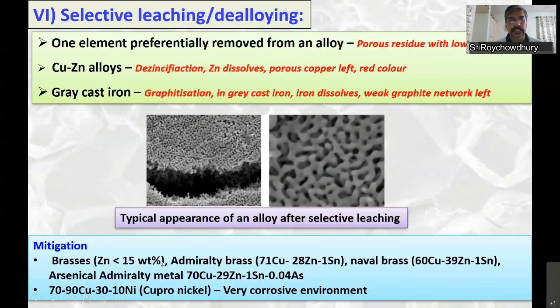Mitigation: use different materials like very low zinc brasses, less than 15%. This problem is more severe in copper 30% zinc alloys. If it is less than 15%, the problem is less. Addition of arsenic or tin will again reduce this problem of selective leaching. If the alloy or the environment is highly corrosive, instead of zinc alloying, go for nickel alloying, like cupronickel, that is very conducive for very corrosive environments.